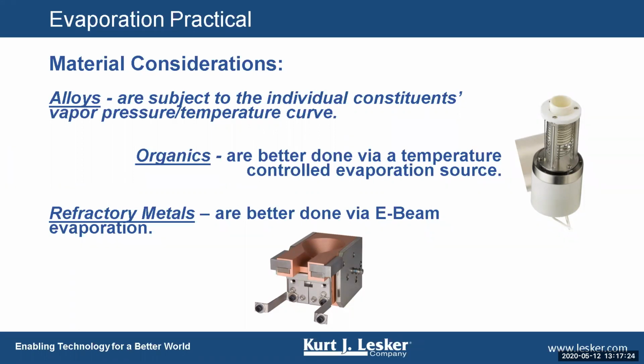so that all the beam is on that one piece of silicon dioxide, it's going to sublime and blow off at quite a rapid rate. No matter how good my PID loop control is, if I get many of those events of rapid evaporation or sublimation, it's going to be very hard to control the rate. So in general, I'm trying to heat up the material as evenly as possible on the surface so that I avoid this rapid sublimation and popping, or rapid increases and decreases in the rate during the course of the evaporation.